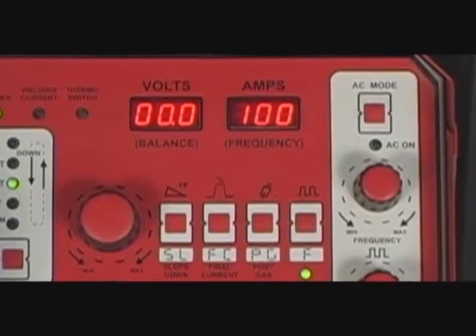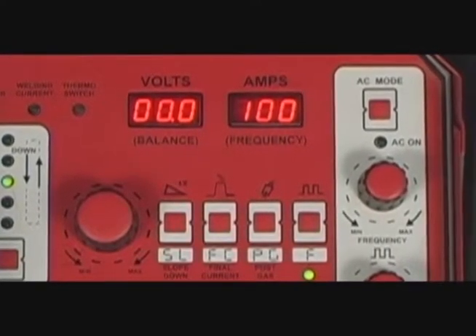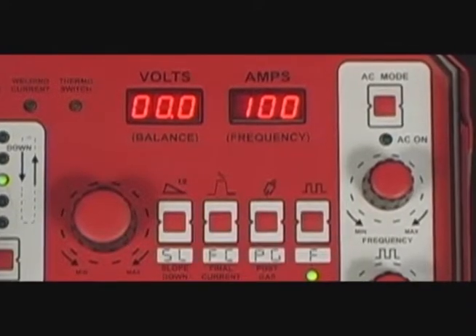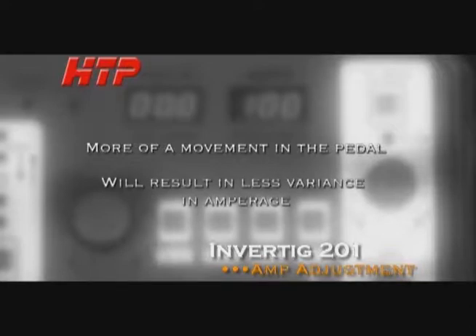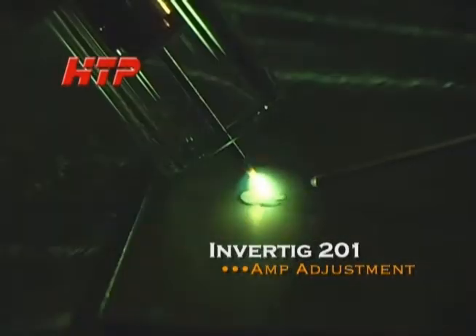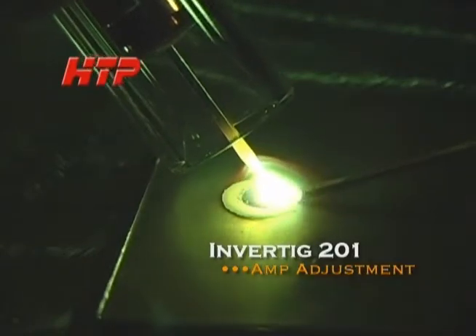Setting the machine so the maximum amperage is limited to 100 amps instead of the maximum output of 200 amps makes the pedal less sensitive. More of a movement in the pedal results in a smaller variance of the amperage, making it easier to control the heat and therefore easier to control your puddle.